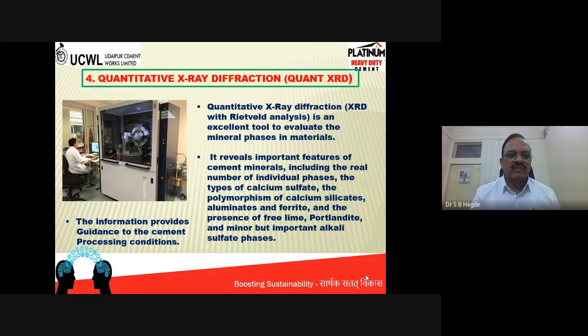For example, you know C3S, C2S, C3A, C4AF. If you take the clinker sample and analyze it through this X-ray diffractometer, you will come to know what type of mineralogy it has, because as you are aware, there are different polymorphic modifications of, for example, C2S or dicalcium silicate: alpha, beta, gamma. So you will come to know by this analysis which form they are in, and how much of it is there.